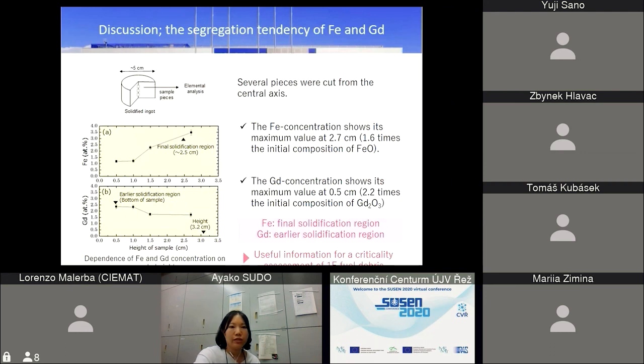This 0 point is the bottom of the ingot, and this 3.2 centimeter is the height, the top of the ingot. The iron concentration shows its maximum value at 2.7 centimeter, near the final solidification region of the melt. On the other hand, the gadolinium concentration shows its maximum value at 0.5 centimeter, near the early solidification region, the bottom of the ingot.